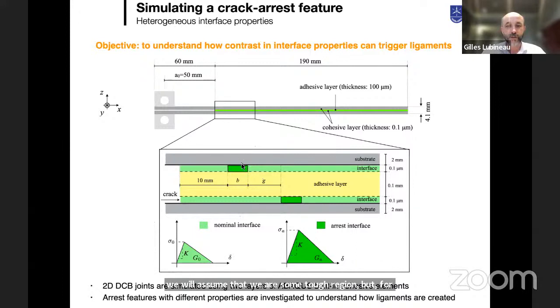dark green here. So if I look at the sigma-delta opening separation curve, the traction separation curve, the stiffness is bigger and the toughness is bigger. If I go on the light green, I introduce some surfaces that are weaker. Experimentally, this is easy to do by using different levels of energy with laser treatment. And then what I would like to see is what's going to happen in terms of delamination if I start to play with the contrast of properties between the dark green and the light green.